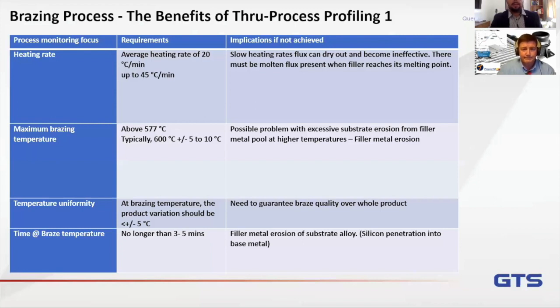Yeah, and thank you for bringing up temperature uniformity. One of the most common questions that we receive is, how much overshoot is acceptable? And our response is always, well, none, zero. Especially when you look at the temperature of your base metal and the temperature of your filler metal, they're so close that even a little bit of overheating is going to affect your base metal. So that's actually the reason no specification allows overshooting. Sorry, it's not going to pass. We need to look at the furnace and see what's going on and fix it.